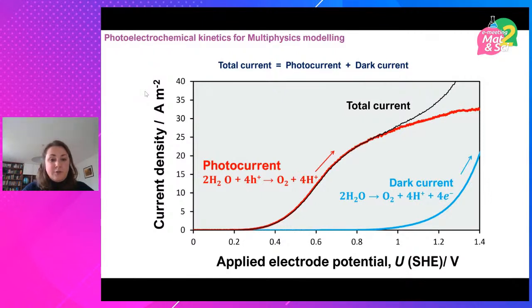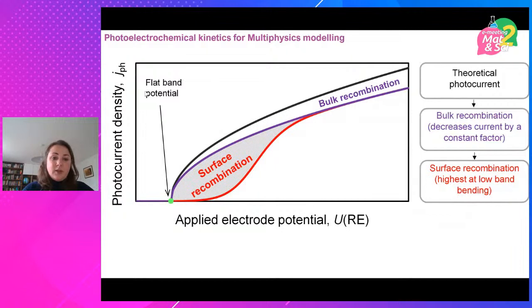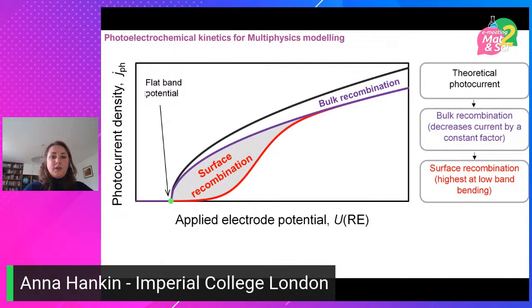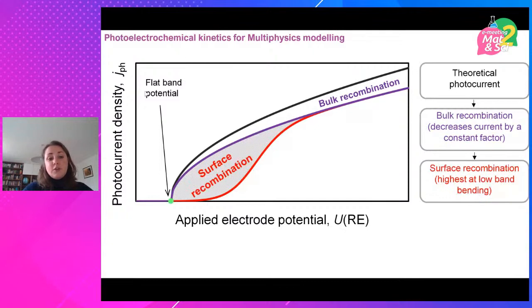So the photocurrent itself can be predicted. It can be predicted using something called the Gärtner-Butler equation, which takes into account things like irradiation intensity, the absorption coefficient of the semiconductor, and band bending, which is very important. So essentially, the photocurrent is proportional to the square root of the band bending of the semiconductor at the semiconductor liquid interface. But the point at which you start to analyze the kinetics, so the sort of theoretical potential at which you have no kinetics, after which photoelectrochemical reactions become possible, is called the flat band potential, right? So it's a very important parameter in modeling the kinetics.